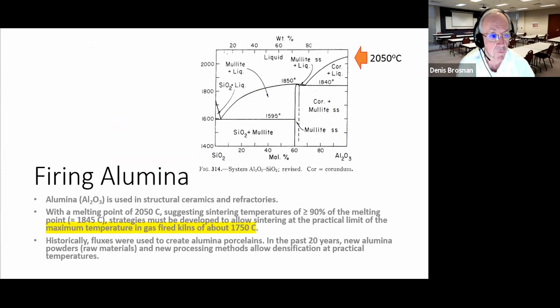Well, enough about review. So today we're going to talk about firing alumina. And of course, I've shown the alumina silica binary phase diagram again. So you know that when you get up here in the 90 to 100% alumina, you expect corundum and mullite to be the equilibrium phases in the product. We, of course, would expect pores and cracks, and we'll find that we can have a little bit of liquid residual in these products on firing.